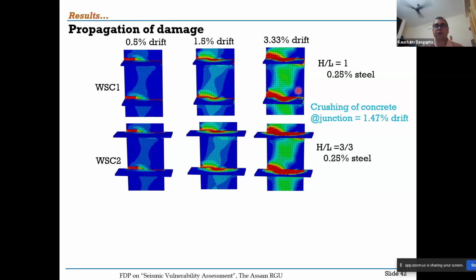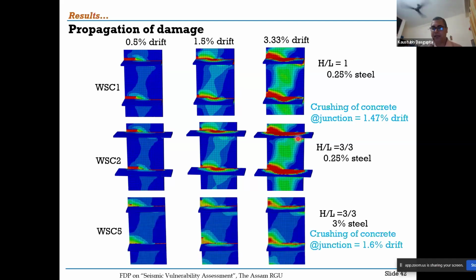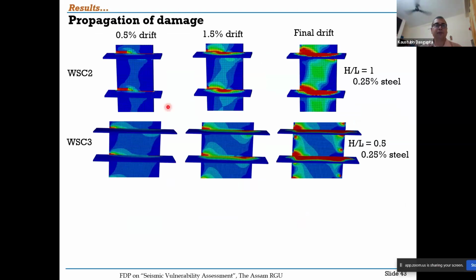You can see very well the strut formation, whether the slab is extended or not. It is getting repeated, and you can see these red zones at different levels. In these two, the steel percentage was less. Here, the steel percentage was more. In certain cases, you have the crushing of concrete at the junction, right? So very interesting behaviors came up. When you play around with these parameters, you can see the variation in the propagation of damage. Then at different levels of drift, 0.5% was very early when the damage just started. This is the moderate level damage, and this is the final drift.